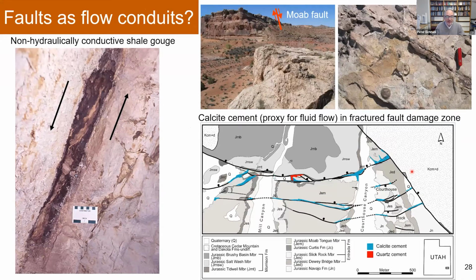Now you may ask, we have been asked, why do you study single fracture growth? Why don't you study the behavior of faults? Aren't faults the structures that control fluid flow? More importantly, a fault would be reactivated at lower injection pressure, then you would form opening mode fractures. For opening mode fractures, even subcritical fractures to form, you would have to exceed the fracture gradient, which in a CO2 reservoir, you would obviously manage the injection pressure, you would avoid that.